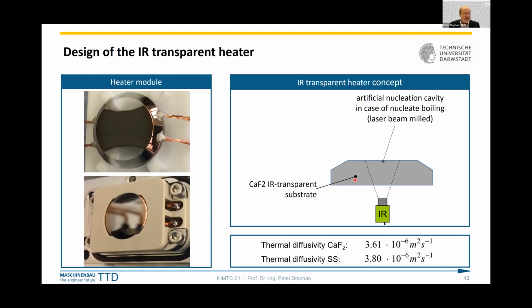In case of the nucleate boiling experiment, we produce with a laser beam a small artificial cavity inside this calcium fluoride glass, about 20 micrometer diameter and about 100 micrometer depth. Of course, in case of the drop impingement experiment, we don't have this nucleation site.